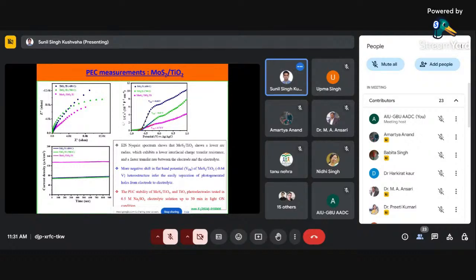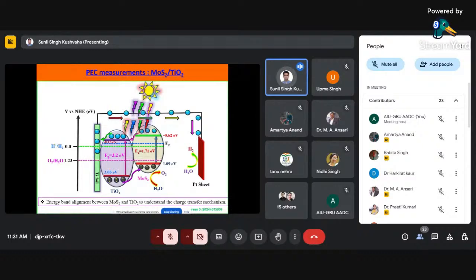So of course, when we go toward how and what is happening, we can see this energy band diagram. Accordingly, it depends on what the band gap is, and how the electron and hole pairs move after generating the electron hole pair in the presence of solar light. We can see the MoS2 band gap is 1.7 electron volt, and TiO2 has 3.2 electron volt. But it also depends on the conduction band edge position and valence band edge position. Accordingly, your Fermi level will shift, then electrons will move from MoS2 to TiO2, and then from TiO2 to the Ti foil, and accordingly your efficiency will decrease or increase. It depends on the band edge position.